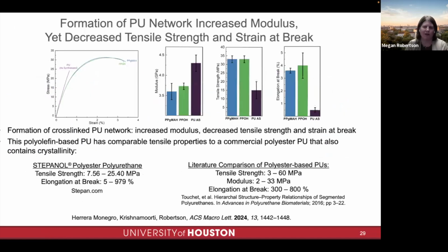Now back to something that's important for applications, which are the mechanical properties. So what are the mechanical properties of these polyurethanes like? By the way, even though we're comparing across our three materials, maleic anhydride grafted polypropylene, hydroxylated polypropylene, and the polyurethane, we're actually even more interested in comparing our polyurethanes to other polyurethanes. But first, let's just look at the properties. The modulus is already quite high for this polypropylene, but when constraining it in the network, it increases further. Those constraints of the network structure also reduce the tensile strength of the polymer and make it quite brittle. So these polyurethanes are fairly brittle.